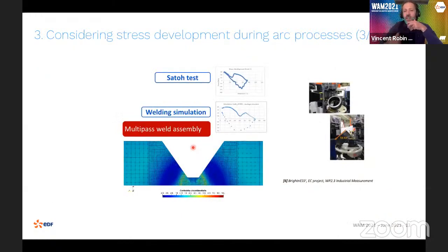And what is interesting is that this Satoh test is really a uniaxial stress test. But if you look at real welding components, when you perform the simulation, you can notice that the stress evolution at some location, for instance in the heat affected zone, is similar. This is the chamfer. This is the added material. This is the section of the tube for the base metal. And you can see that the stress response in the heat affected zone is very similar to the one we have in the uniaxial test. Just note that this component was used for the industrial measurements of one of the work packages of the BrightnESS² project.